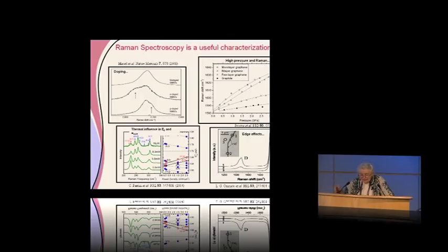So if you know that, you can do a lot of things. You could study pressure dependence, and you could see here for different amounts of applied pressure, you get shifts. This is uniform squeezing. We had stretching mostly in the talks. You could do stretching here too, and that gives you something similar. Temperature effects, that's another thing.